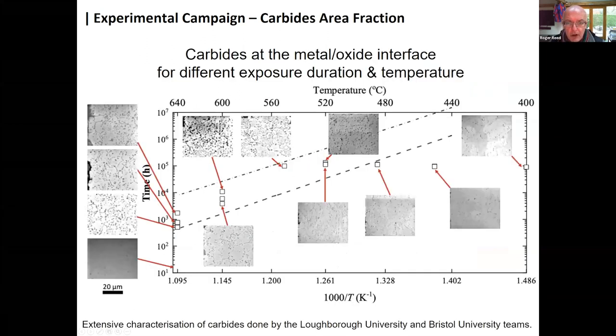And again, more evidence here. You can see a logarithm of time and reciprocal temperature, but the corresponding temperature on the top of this graph. If we look at the data at 640 degrees Celsius, you can see over time, with increasing time, the interface between the metal and the scale in the metal is becoming progressively decorated with more and more carbides. So there is actually evidence also of an enrichment of carbon at that interface, which gives us an issue around how to handle that boundary condition in the model, which I'll tell you a few things about in just a few moments.